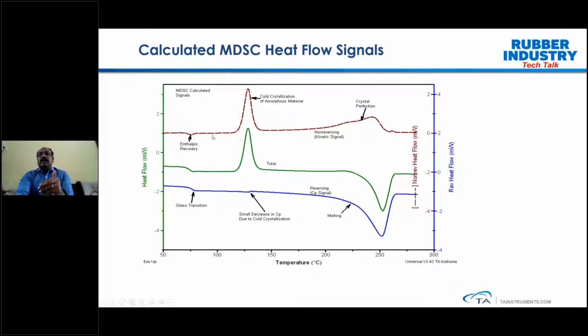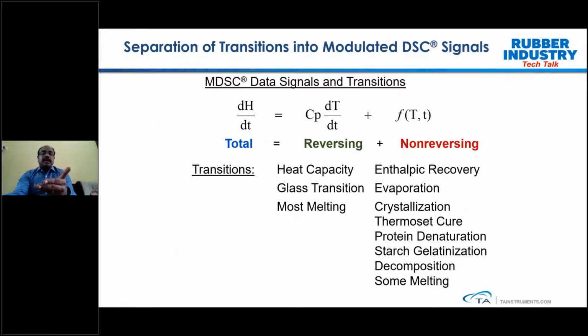Another is the non-reversible heat flow, which shows all the kinetic events. You can even see a small endothermic peak occurring close to the glass transition, which is because of enthalpic recovery, followed by crystallization and then crystal perfection. This way, you are better equipped to detect where exactly the glass transition temperature is, and it also looks much broader and detectable. So that's what we are talking about here.